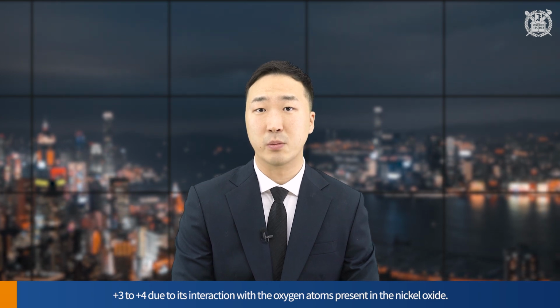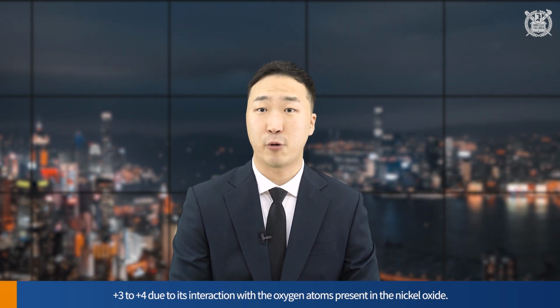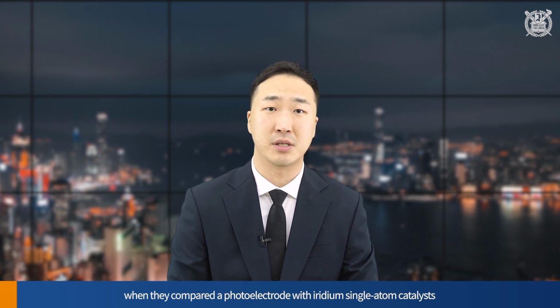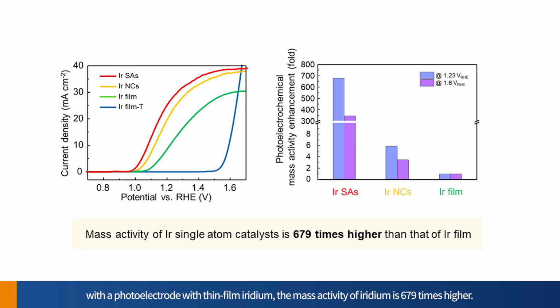The iridium single atom obtained in this way has a unique oxidation number of +3 to +4 due to its interaction with the oxygen atoms present in the nickel oxide. Professor Chang Oh-won's research team has demonstrated that when they compared a photoelectrode with iridium single atom catalysts with a photoelectrode with thin film iridium, the mass activity of iridium is 679 times higher. This is a result of the independent existence of all the iridium atoms, maximizing utilization efficiency. These single atoms have an enormous potential in the field of catalysts for green hydrogen production.